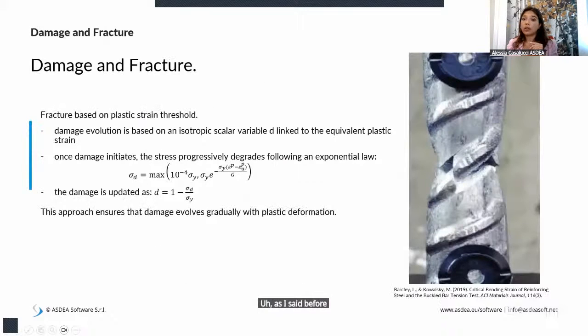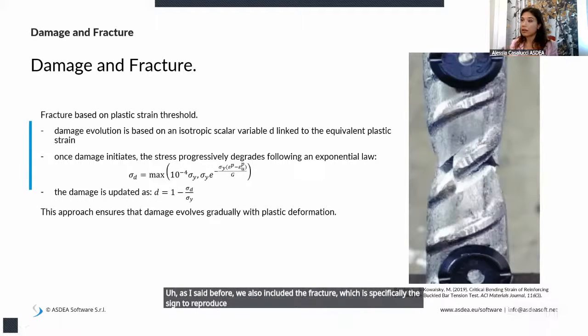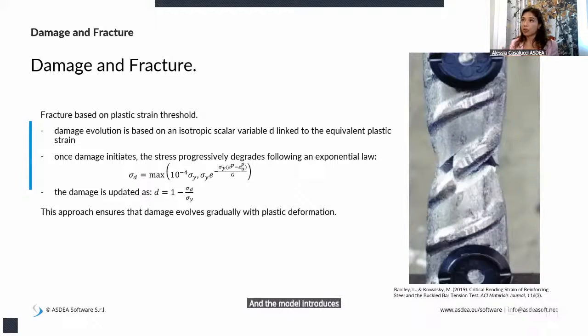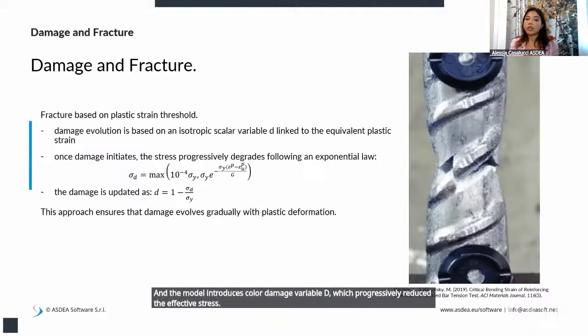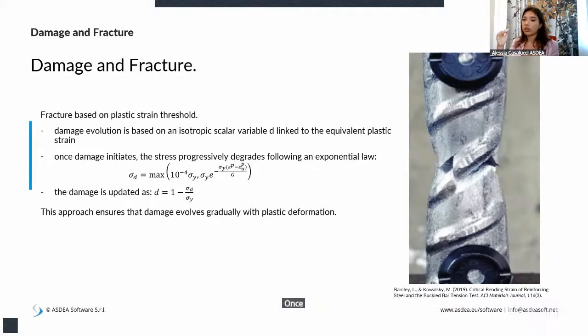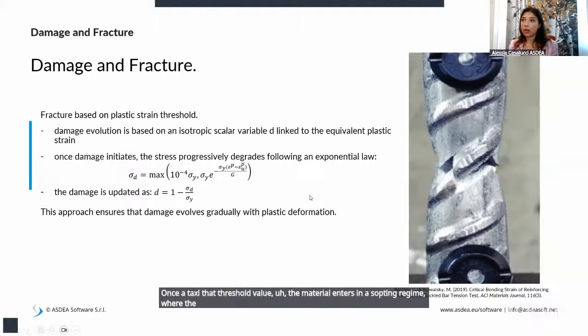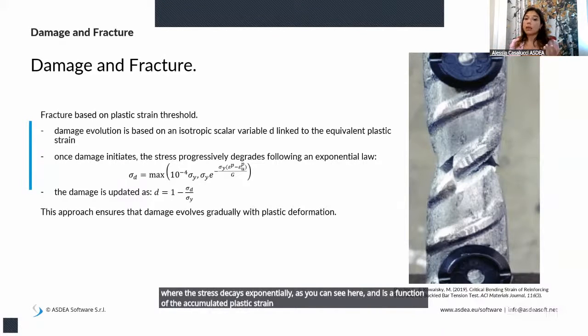As I said before, we also included the fracture, which is specifically designed to reproduce the tensile rupture of steel bars. The model introduces a scalar damage variable, D, which progressively reduces the effective stress. The damage activation is governed by the equivalent plastic strain. Once it exceeds a threshold value, the material enters a softening regime, where the stress decays exponentially, as you can see here, and is a function of the accumulated plastic strain. This enables the material to simulate bar rupture under tension.